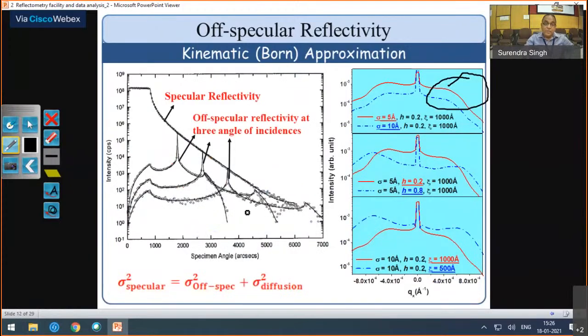Typically in reflectivity, here I have shown this specular reflectivity going all the way down. And then we have collected the off-specular reflectivity at a particular angle of incidence. So we situated at this angle of incidence and got this off-specular reflectivity. At another qz value, another angle of incidence, we have another reflectivity. So we have three off-specular reflectivity curves and one specular reflectivity.